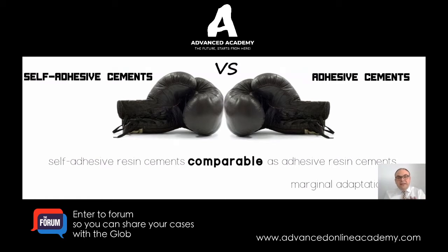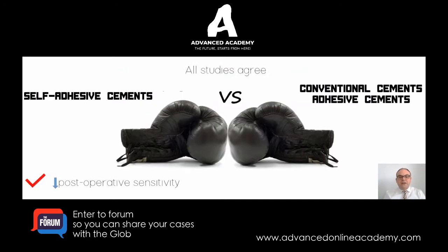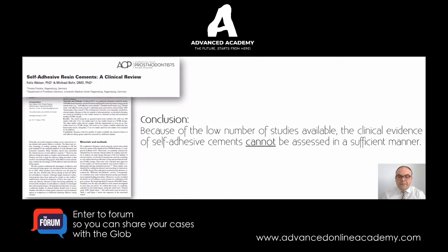To make it easier for you, whenever you're doubting your resistance and retention form, I would really go towards an adhesive cement, because it's going to have a little bit of an enhanced bond strength to the tooth structure. When self-adhesives were compared to conventional cements and adhesive cements, the self-adhesives had less post-operative sensitivity. Because of the limited trials, the author concludes here that the clinical evidence of self-adhesive cements cannot really be assessed properly because of the lack of information that we have.